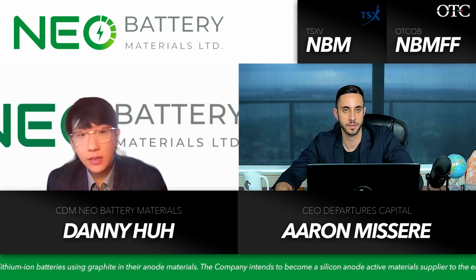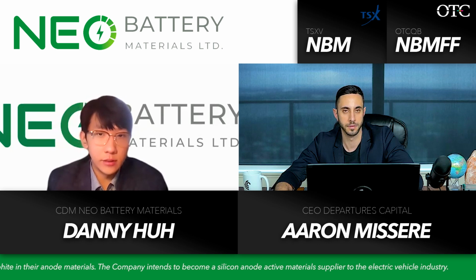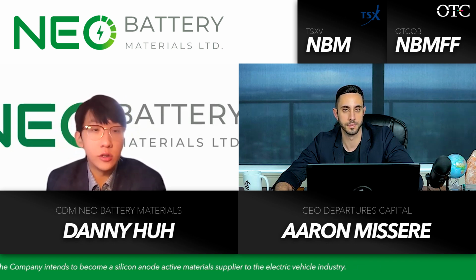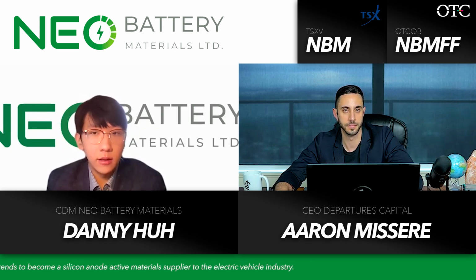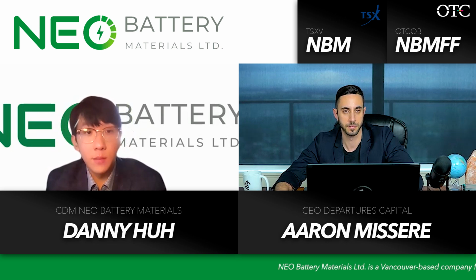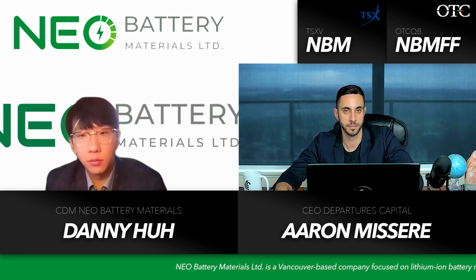But there is a technical problem with silicon, and this is why the industry can't massively use it. There is a natural volume expansion that occurs when we charge our silicon. And what happens is that it expands by about 300%, which is 4 times. And after only 100 cycles, it's not usable. So right now on the commercial level, it's very hard to use silicon. So the industry is formulating unique manufacturing methods and solutions and know-hows to solve this problem.